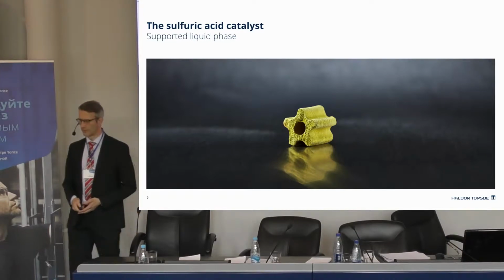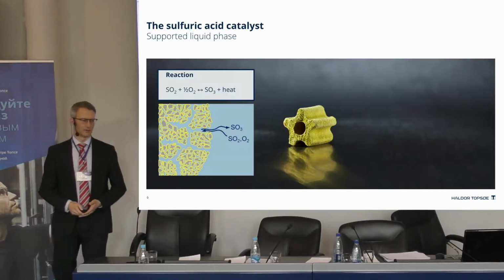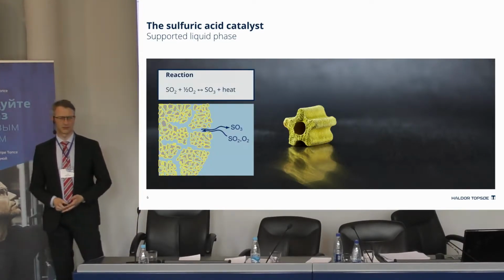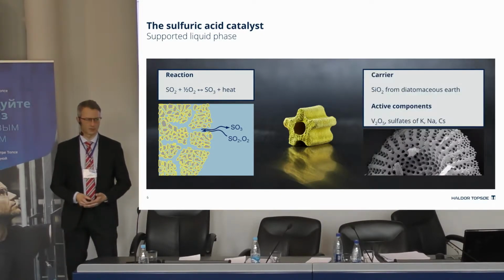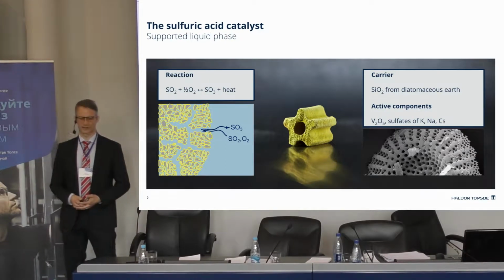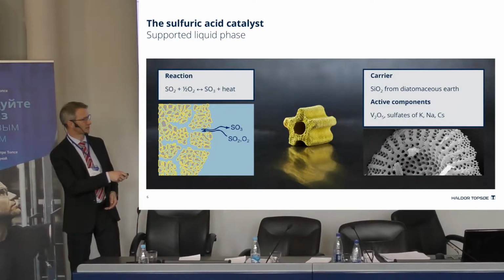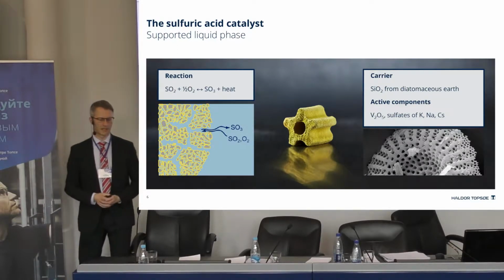The sulfuric acid catalyst may look like this, and the purpose is to oxidize SO2 to SO3, which is a reversible exothermic reaction, and the catalysts are based on a silica carrier, and the silica comes from diatomaceous earth. You can see a single diatomaceous earth particle here. And the active components are vanadium oxides and alkali metal sulfates.